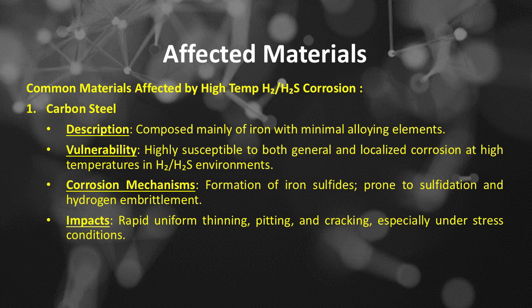Common materials affected by high-temperature hydrogen (H2) and hydrogen sulfide (H₂S) corrosion include, number 1, carbon steel. Composed mainly of iron with minimal alloying elements, the vulnerability of the carbon steel: highly susceptible to both general and localized corrosion at high temperatures in hydrogen (H2) and hydrogen sulfide (H₂S) environments. Corrosion mechanisms commonly affecting the carbon steel: formation of iron sulfides, prone to sulfidation and hydrogen embrittlement. The impact of high-temperature hydrogen (H2) and hydrogen sulfide (H₂S) corrosion on this carbon steel is rapid uniform thinning, pitting, and cracking, especially under stress conditions.